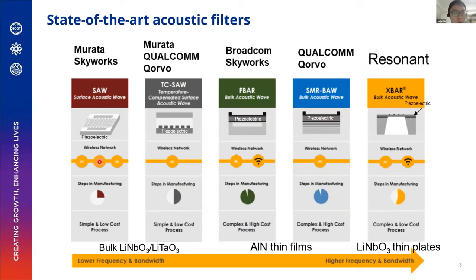For previous generations like 2G or 3G wireless networks, they use so-called surface acoustic wave resonators. It's basically a piezoelectric single crystal like lithium niobate or lithium tantalate. You pattern interdigital electrodes on the surface to generate the acoustic waves on the surface of the crystal. Those have limitations: they cannot go to very high frequency because of the finger width of the patterns of these interdigital electrodes. People have also been developing temperature compensated SAW to get better temperature stability over a wider working temperature range.